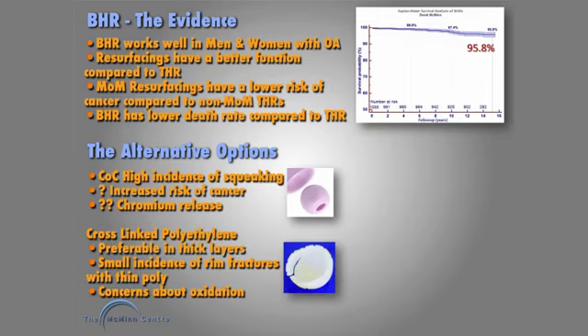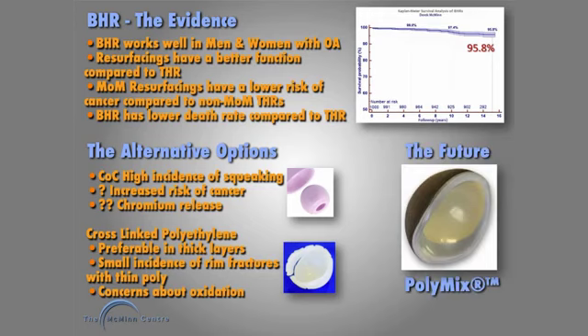With polyethylene, the preferable polyethylene now is cross-linked polyethylene, which has much lower wear than conventional, but is best used in thick layers. There is a small incidence of rim fracture with a thin poly cup and a highly inclined implant. And there are some concerns about oxidation. Some studies have shown a 20% oxidation rate at 2+ years on retrieval studies. What we're interested in at the moment, particularly for patients with known metal hypersensitivity, is a hybrid component called Polymix, where the articular zone is cross-linked polyethylene and the periphery of the cup is the stronger conventional polyethylene. And time will tell if that turns out to be a preferable implant. I thank you for your attention.